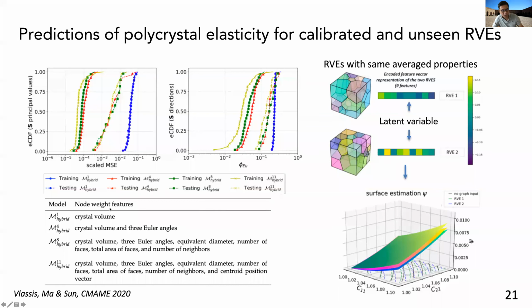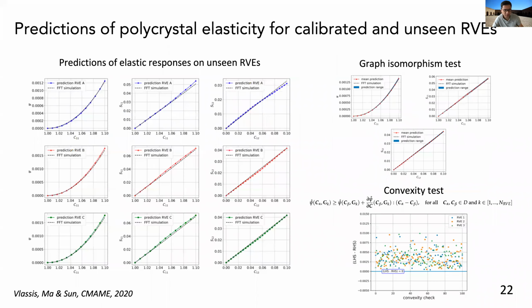We can also see how different features that we put in affect the resulting elasticity predictions. For example, if I just put in the volume, I get the blue curve, which has quite a bit of error, on the order of 10 to the minus 2, 10 to the minus 1. But if I add more features, I move the curve to the left-hand side. At some point, if I add too many pieces of information, the difference becomes very small. That gives us the flexibility to introduce different microstructure information and put it into the graph convolution to generate different types of low dimensional representations of the microstructure system.